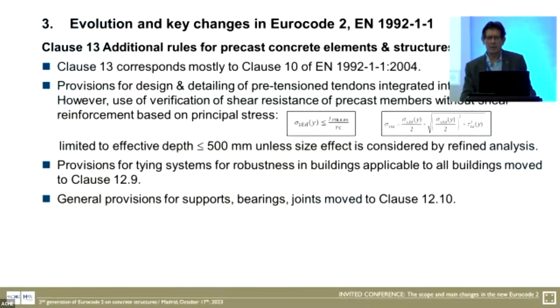Clause 13, precast elements and structures, basically that's the same as in current Eurocode clause 10, but we have moved the provisions for pre-tensioned concrete from the current section into this clause 13 because we recognize that pre-tensioning is mainly used together with prefabrication. So design and detailing rules now in clause 13 for pre-tensioned tendons, and there we have changed one provision in particular I want to highlight here, which is the verification of the shear resistance with the principal stress criteria. We have limited the use of these provisions now to members of a maximum depth of 500 millimeters. If somebody wants to use this for taller members, they will have to consider the size effect in a refined analysis.